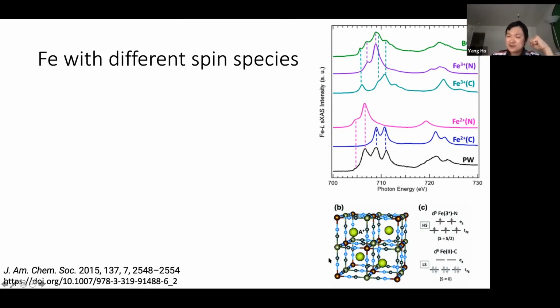ferrocyanide. So there are two types of iron environment: the iron that's coordinated with the carbon atoms of the cyanide, and the iron coordinated with the nitrogen atoms. So the carbon end is believed to be a strong ligand. So the carbon side favors the low spin, what we call the low spin iron site. And the nitrogen side is a weak ligand, so it's a high spin iron site.